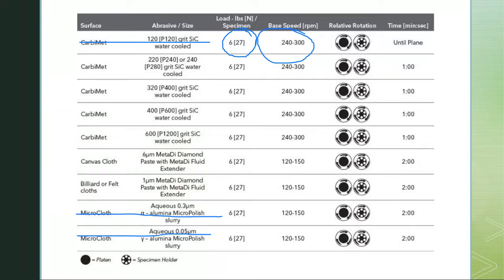So 200, 240 to 300 is typical range when you're in the silicon carbide grinding stages. Okay, and you can see that's carried out all the way till you get to about here. You maintain the same. Now you see that when you reach the polishing portion, all of a sudden the force stays the same, but your RPM now decreases.